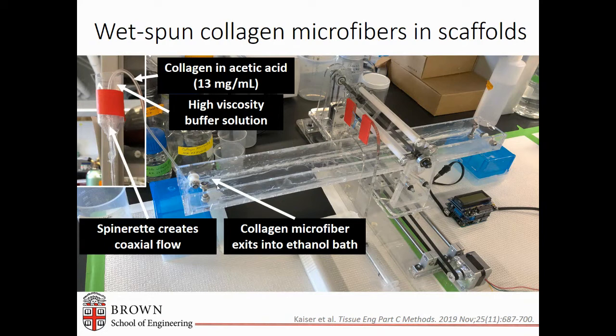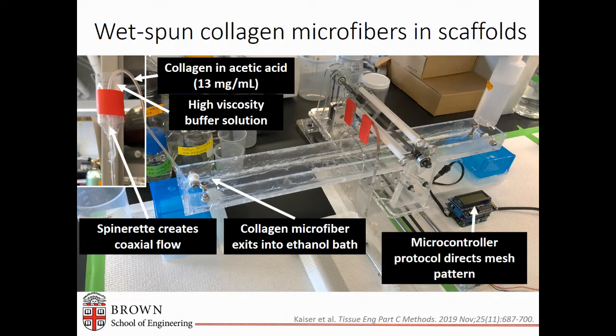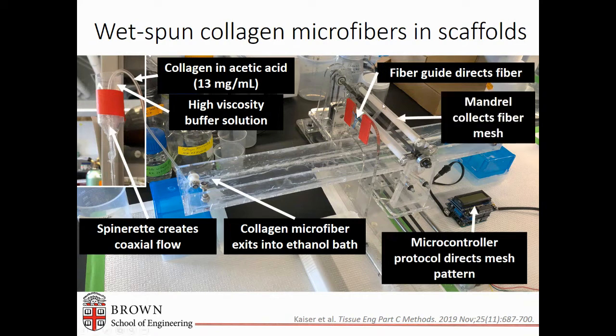We're going to use some robotics controlled through a microcontroller, and we feed those fibers through a guide that then can go onto a mandrel to collect meshes that are programmed through the microcontroller, which controls two motors, one that causes rotation of the mandrel and the other that causes lateral translation.